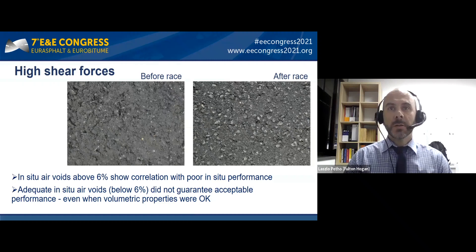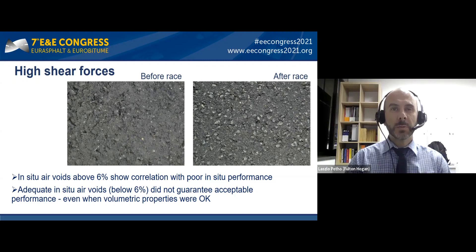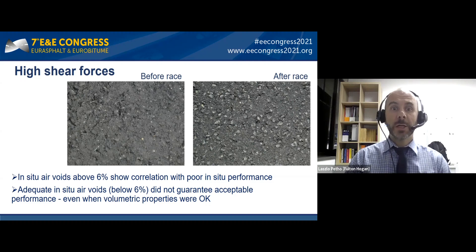As you can see in these before and after photos, you get a lot of binder wear-off after the race — very harsh racing conditions. In the past, if air voids were above six percent it was always linked to poor in-situ performance, while if air voids were below six percent it didn't necessarily provide good performance. This was a pretty big challenge for us.